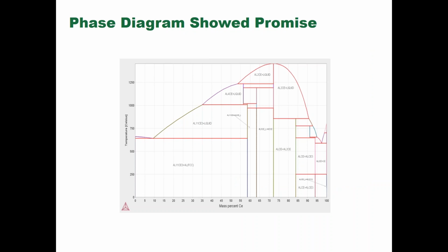There's not a lot of phase diagram information, although Mondolfo did some years ago that we believe turned out to be fairly accurate. This is a computed phase diagram done by the folks at Lawrence Livermore, and we see a lower melting eutectic point at about 10% cerium. That really gave us some hope that we would have an alloy that you could get a substantial amount of the alloying element in and not create a lot of difficult casting problems because of it.